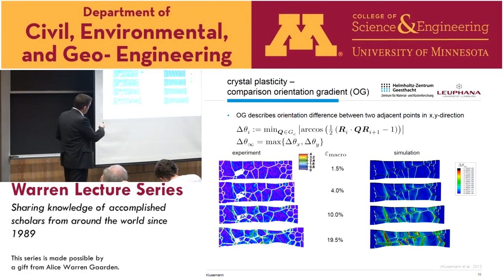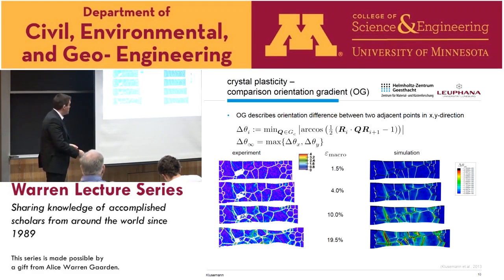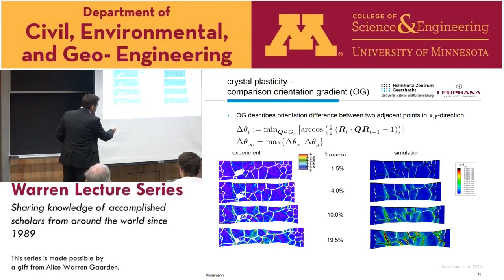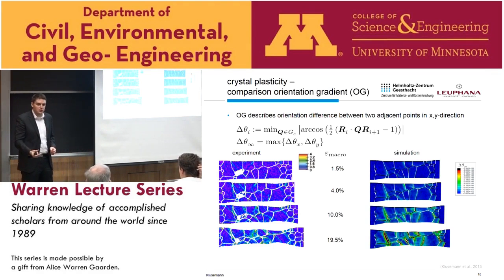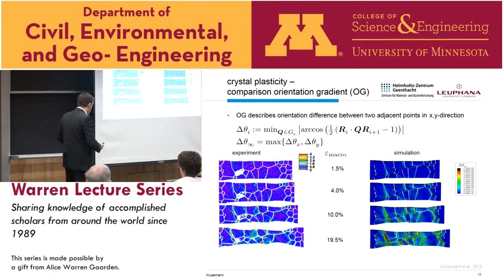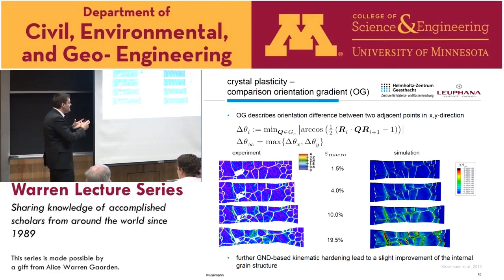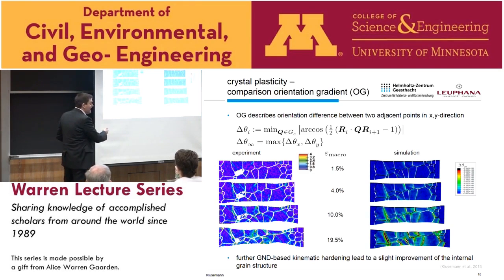So first of all, we compared this, of course, to the results of the simulation before, which you can see here. And interestingly, we saw some similar tendencies. So here you saw a strong band, which you can also see here. And also this region, which shows a kind of high orientation gradient, was also predicted by the simulation. And we thought from this point of view that a further GND-based kinematic hardening would lead to a slight improvement at least, which we also investigated then based on a non-local model formulation.